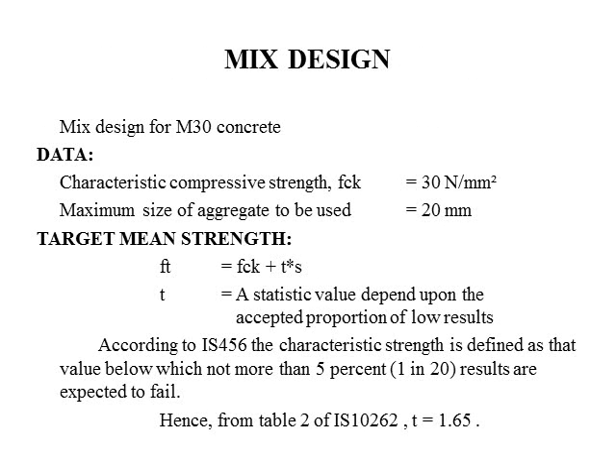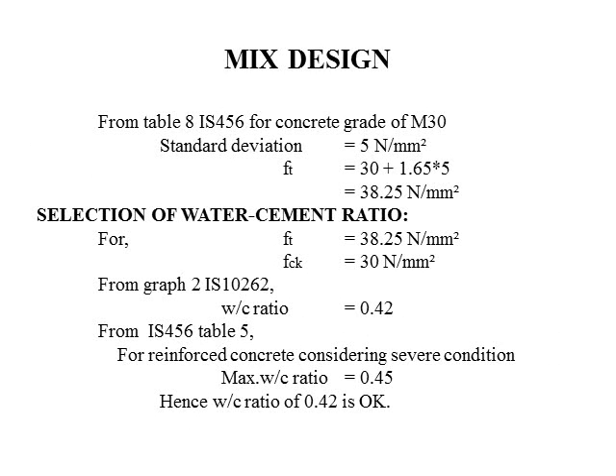Mix design. We have done the mix design according to IS 10262 for M30 concrete and the maximum size of aggregate used is 20 mm. The target mean strength obtained is 38.25 Newton per mm square and the water cement ratio from the graph is 0.42.